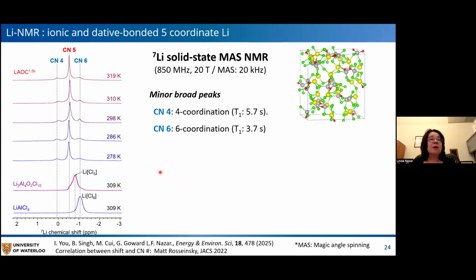So the coordination of lithium in the system is quite interesting. This just shows some solid-state lithium-7 NMR data, comparing lithium aluminum chloride with a lithium aluminum oxychloride, which has 5-coordinate lithium with our material. And again, you can see one major peak here. We assign this a coordination number of 5, and this comes from data of Matt Rosseinsky, which basically shows that there is this consistent shift in frequency as you go from 6 to 5 to 4. This was for a different class of materials, but it holds for these as well.